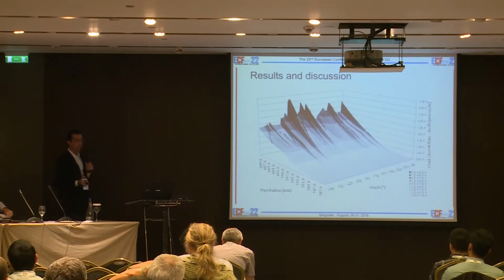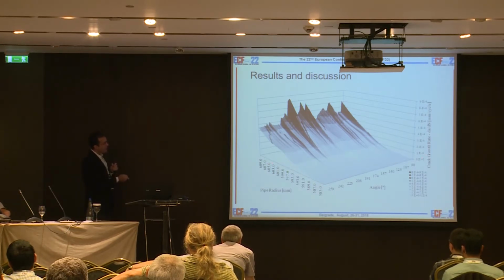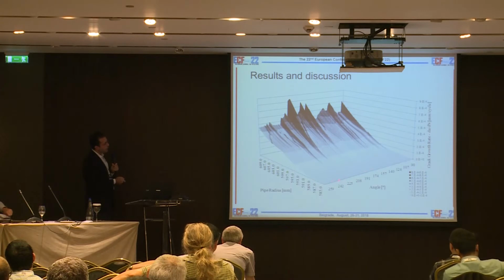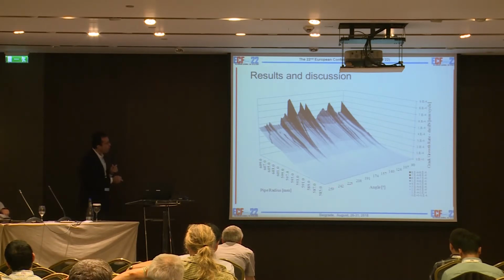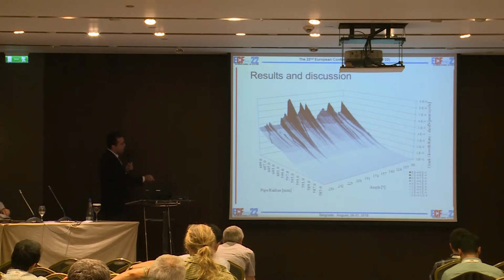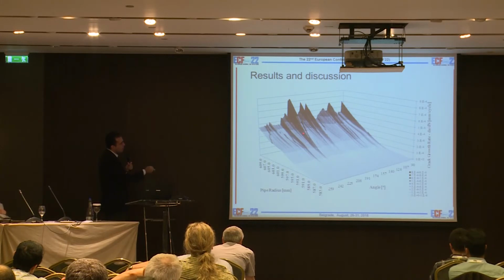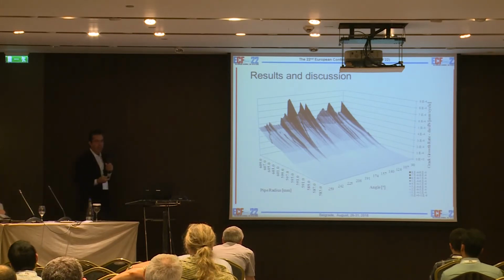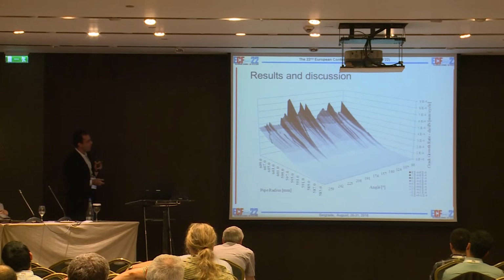This is an example of da/dN, crack growth rate, from the inside of the pipe to the outside in terms of the angle. So you can see that, sure, if the plastic prestrain is different, if we take different angles for the case of UOE, in some portions crack growth will be slower, in some portions crack growth will be a little bit faster. This is just to show you examples.